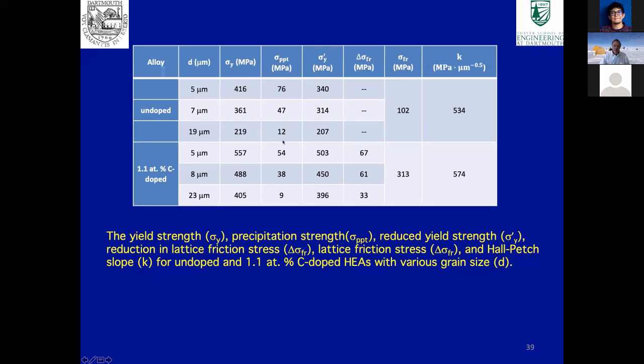For the carbon doped material, not only do we have a precipitate strengthening, which is actually in some cases quite small, but we've also removed carbon from solution, which is a very large strengthening to the material. So we've actually lost this strengthening from the carbon. So we've got strengthening from precipitates, but we've lost this. So we can recalculate the strengthening in the material when we take into account those two factors.